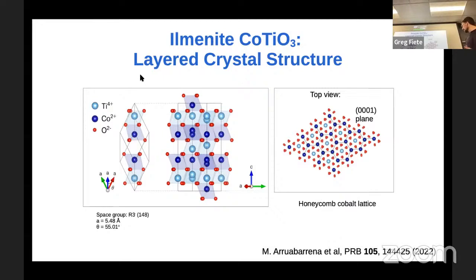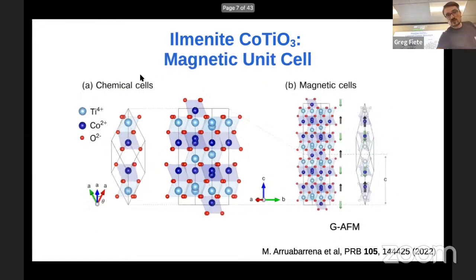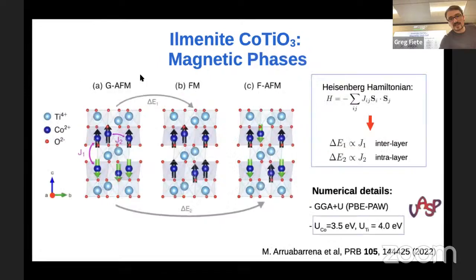So once that we have seen a little bit the structure, let's move to the magnetism. In order to study the magnetism, the first thing we had to do was to take into account a proper magnetic cell, let's say, because if we just took the basic chemical cell, some magnetic configurations, such as the experimentally observed ground state, G-AFM, were not accessible. So we had to use a larger unit cell to include all this up, down structure. We will look at it in a moment. So how do we study the magnetism of these compounds via DFT?